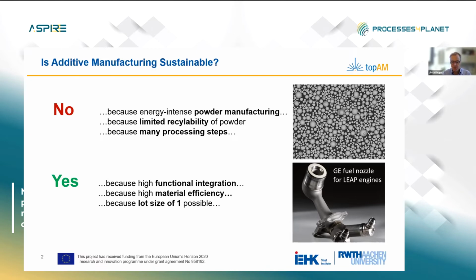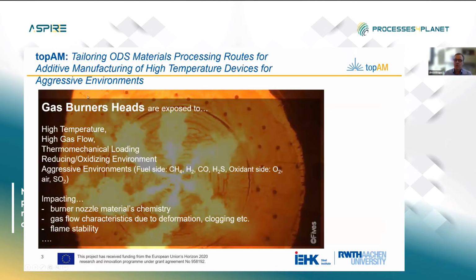A good example where it can be sustainable, and that is where TOPAM, our project, comes into the game. These are gas burner heads in process engineering, and these kinds of gas burner heads are exposed to high temperature, aggressive environment, high gas flows, thermomechanical loading, reducing and oxidizing environments. So there is a high potential for improvements in terms of increasing the service life, optimizing gas flow characteristics, and increasing the temperature, so that by doing it with additive manufacturing, we may end up in a higher efficiency of process engineering steps.